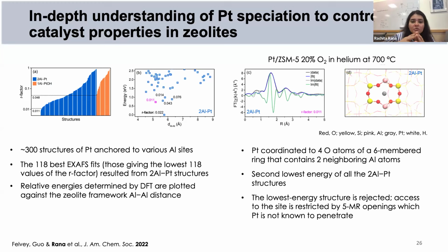And then what we found was that this was a platinum coordinated with 4 oxygen atoms and 2 neighboring aluminum atoms in a 6-membered ring. And what was interesting is this was not the most stable structure. So if we were going by DFT intuition, we would have thought that there's another structure that's more stable and that's going to be our best fit. But that most stable structure did not give us the best EXAFS fit. So the combination of the most stable structure and a decent EXAFS fit was the one that you see here, which was the second most stable structure in the database.